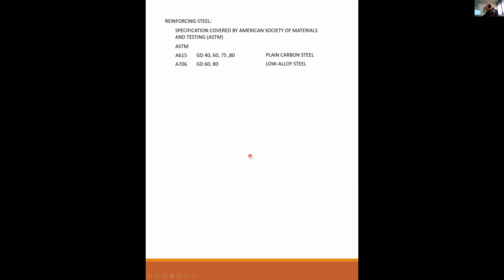A706 is what's known as a low alloy steel. A706 used to be known as A706W, which stood for weldable. So A615 is actually weldable, but you have to be very careful about it. You have to qualify the welding exactly how you're going to do it to make sure you're not going to get cracking. This type of rebar is more prone to cracking when you do the welding. And you usually have to employ preheat or other techniques to prevent undesirable cracking, mainly. Whereas A706